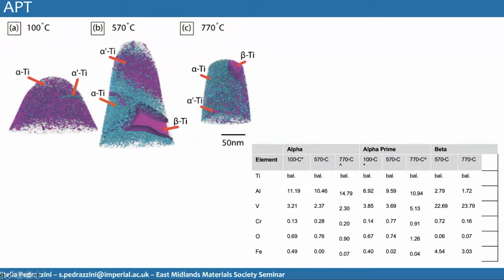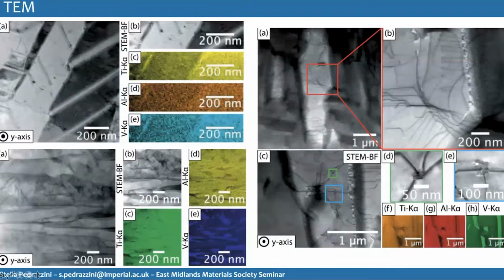The 100 degree sample could still accommodate 0.5% oxygen and have some ductility, and the 570 degree sample could accommodate 0.7% oxygen and have some ductility. So I'm quite surprised at that as well. Clearly, the oxygen uptake has been increased quite a lot by 3D printing at temperature. But this is quite interesting. And then at 770, we've upped the oxygen content so much that clearly there's no more ductility. Also, the dislocations don't look like they could be moving. So they're very entangled, and they look cross-slipped to me, but it's quite hard to tell.